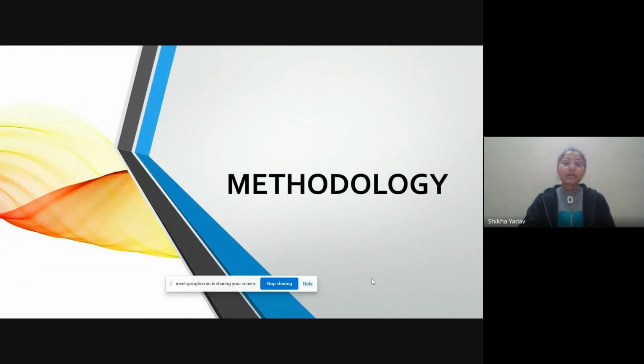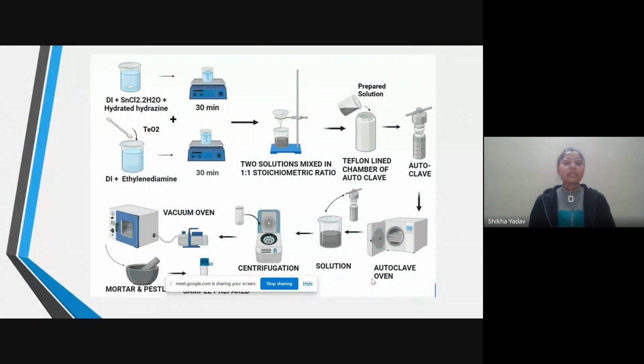So next I'm going to talk about the methodology that I adopted in my research. The process started with dissolving DI water, tin chloride, and hydrated hydrazine. These three were mixed in a beaker, and after mixing, the beaker was kept on the magnetic stirrer for 30 minutes. We took another beaker in which DI water and ethylenediamine were added. In this mixture, we also added the tellurium oxide, and again this beaker was kept on the magnetic stirrer for 30 minutes. After that, we mixed the two solutions in a 1:1 stoichiometric ratio.